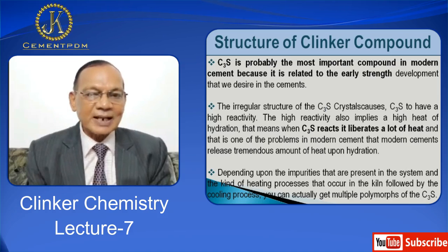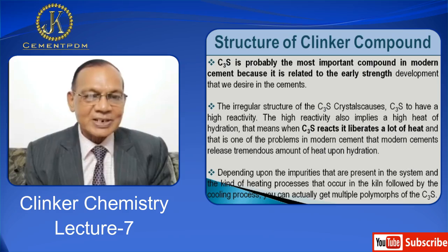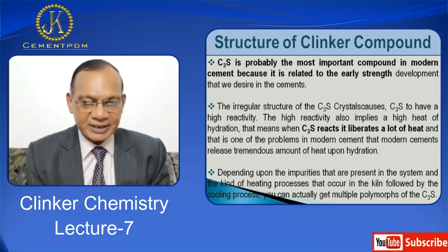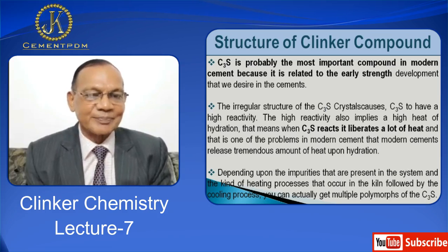The irregular structure of the C3S crystal causes C3S to have a high reactivity. The high reactivity also implies a high heat of hydration. That means when C3S reacts, it liberates a lot of heat, and that is one of the problems in OPC. That OPC releases tremendous amount of heat upon hydration.